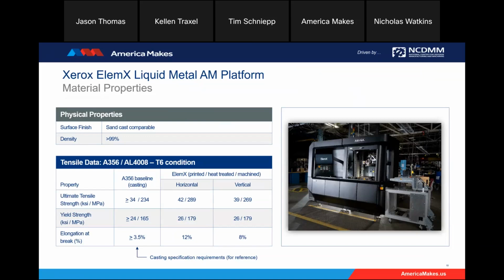And there's no HIP process or those types of post-processing required to achieve these densities. We did some evaluation of those types of approaches and didn't see much improvement at all. So it's not something we recommend or require. Some porosity is inherent to this process. If you picture the jetting process, the droplets of molten aluminum come out as spherical in nature. It's a 500 micron orifice that's used for the jetting, so they have that half millimeter diameter. And then as they land on the build plate or the subsequent build layer, they flatten out a bit, taking on a disc-like profile or a pancake-like shape.